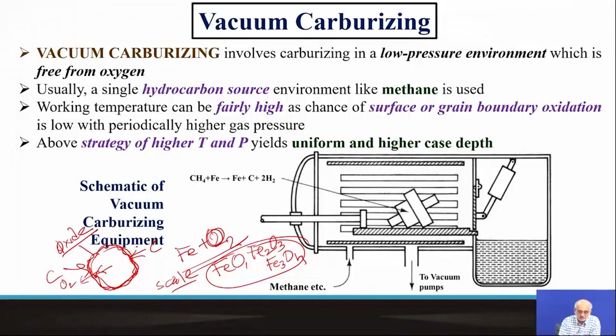So in order to avoid all those, one of the most assured processes would be something like this, where you first evacuate to a reasonable vacuum, 10 raised to minus 3 to minus 5 millibar pressure, and then backfill with carbon containing gases, say unsaturated hydrocarbons, which will eventually dissociate and give methane, and then we'll get carbon coming out of this. And that carbon gets adsorbed to the surface, and that surface is now case hardened.